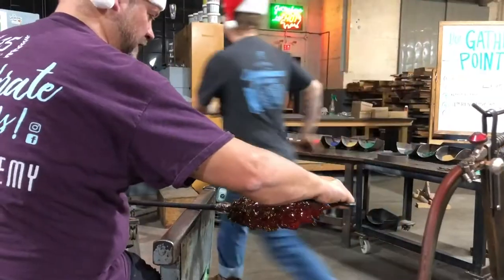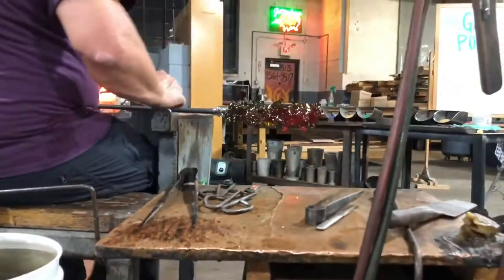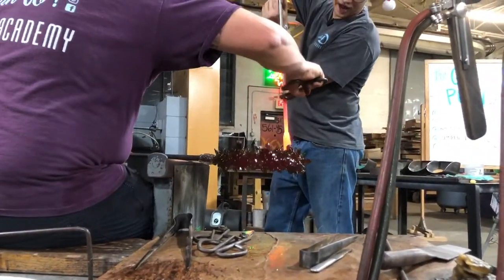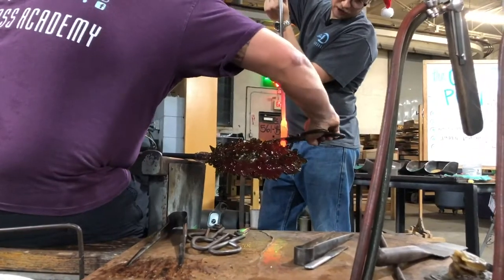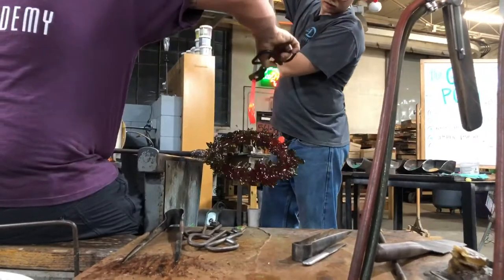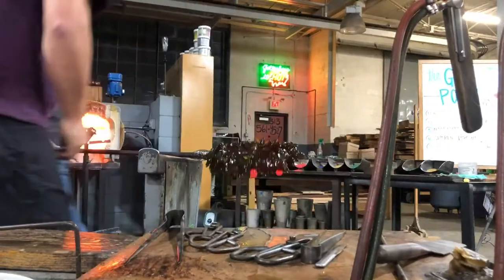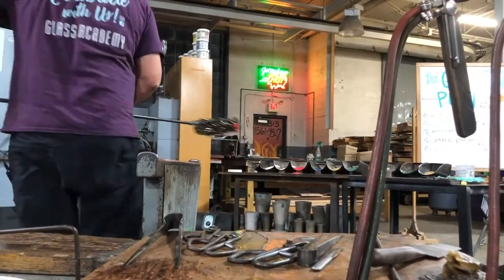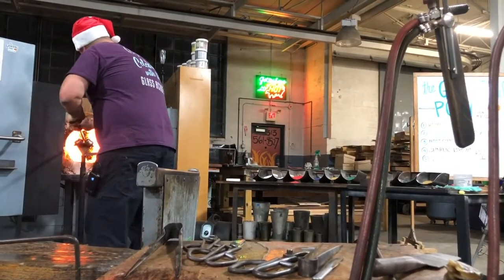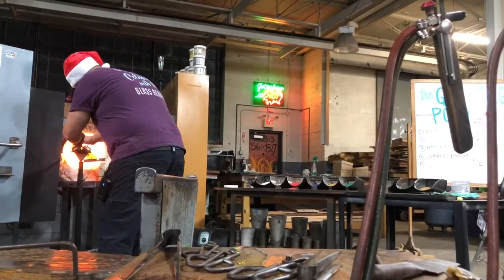One sec. Flattening out our wreath because really it's warping at the ends. Okay, I'm ready. Really tough, actually. The green bits were not so bad with a glory hole to get hot, but red berries here. Red, as many of you know, is the stiffest color we've got, at least most standardly. I'm trying to get this thing hot, but you see how difficult it is for him to cut it. When I'm running back and forth from the hole, that extra 3 seconds outside of the heat does make a huge difference. Gotta keep the heat.